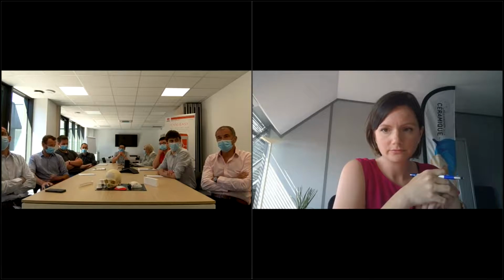So in all our formulations, we have a very high solid loading. That's the reason why we started to use paste, and now we manage to obtain the same solid loading in our cream as in the paste. So it's the guarantee that you will have a very good ceramic density after sintering. The question you answered was about the ceramic loading we are using, which is about 50% up to 65%.